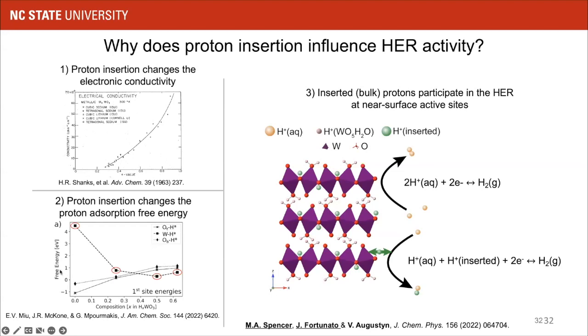Another hypothesis, more recent, comes from our collaborators in the McKone group, where they have evidence that proton insertion actually changes the adsorption free energy for protons for the HER. And then something else that could potentially be taking place is if these inserted or bulk protons are actually participating in the HER at near-surface active sites. So these are some hypotheses that we're testing out and still to be determined for this class of materials. But we've shown definitively that the proton insertion must take place in order for the tungsten oxide surface to be catalytically active.